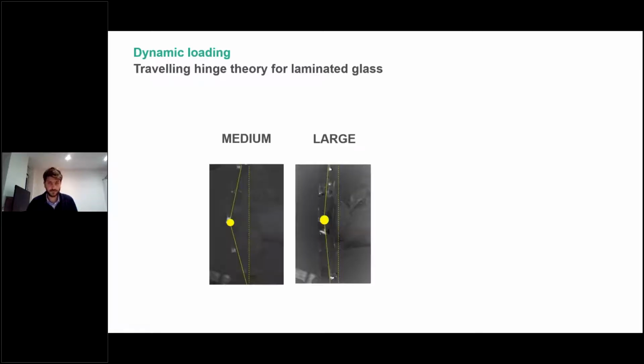The deformation patterns recorded with a high-speed camera demonstrate that the theory of traveling hinges applies to laminated glass. A global collapse mechanism, with the specimens deforming as two rigid bars connected with a single plastic hinge at midspan, was observed for the medium and large specimens. This agrees with a well-known collapse mechanism forming in simply supported beams under a static point load at midspan.